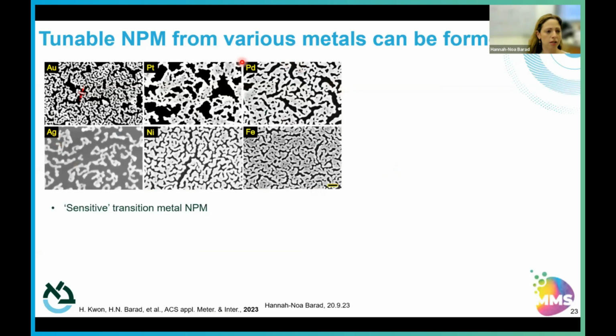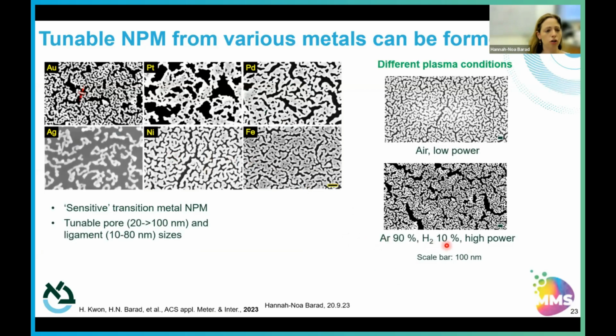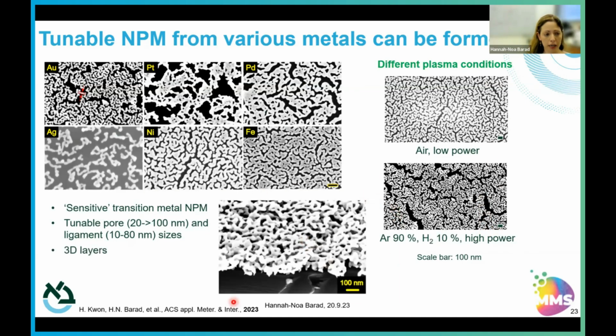So we can form these nanoporous metal films, using them even for sensitive metals such as iron and nickel, which could etch out with some of these corrosive etchant environments. We can also, using the different plasma conditions, control the pore sizes and the tunability of the ligament sizes, so shapes and kind of structure. And also we can make 3D layers of these different types of nanoporous metals. So pretty much we're covering very thin 2-3D layer, and it's a really robust technique.